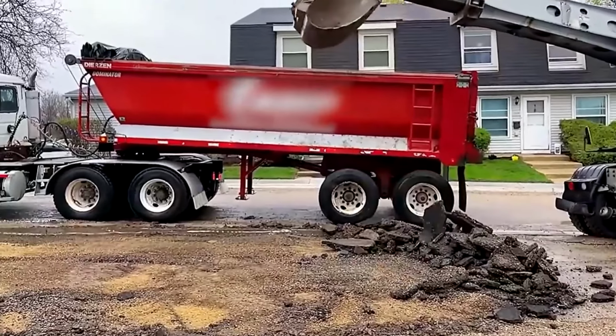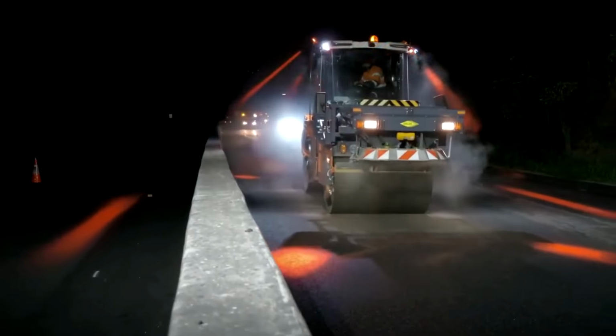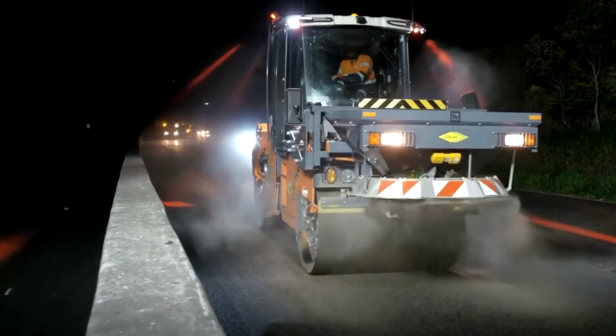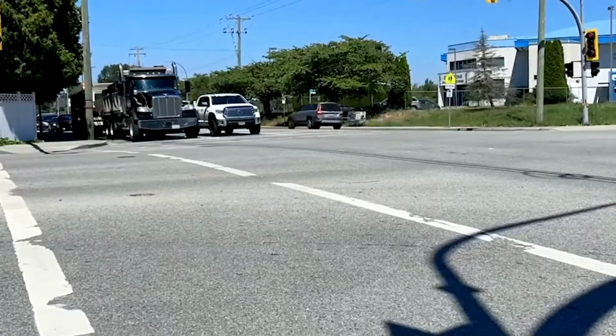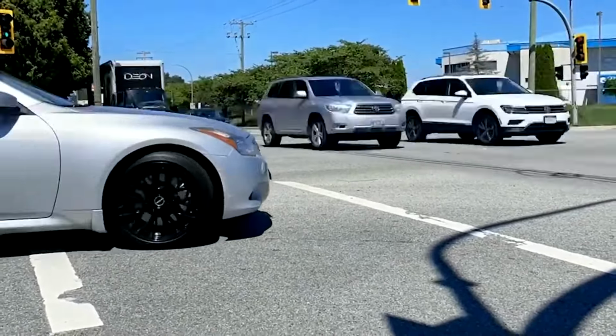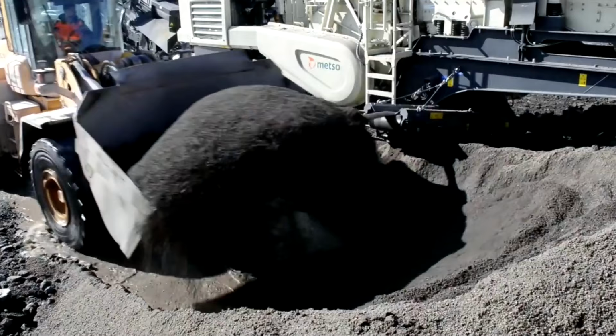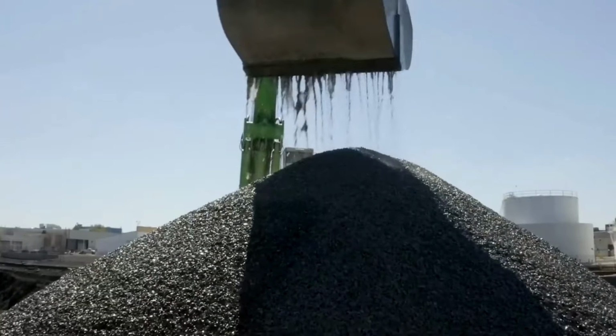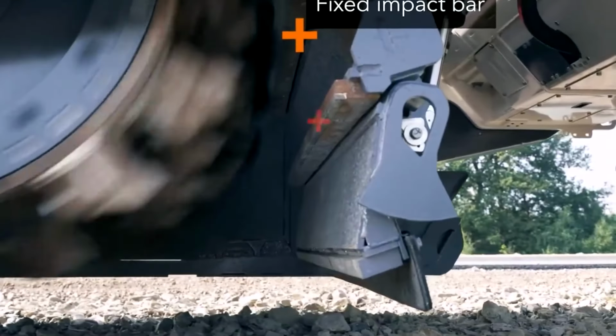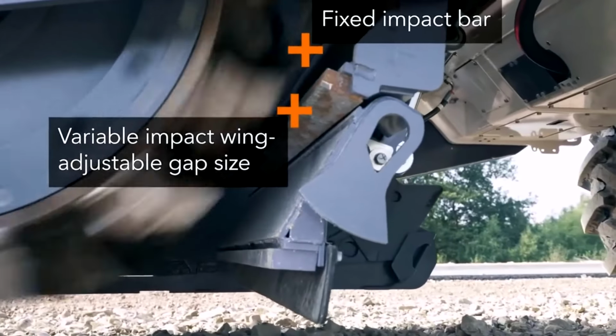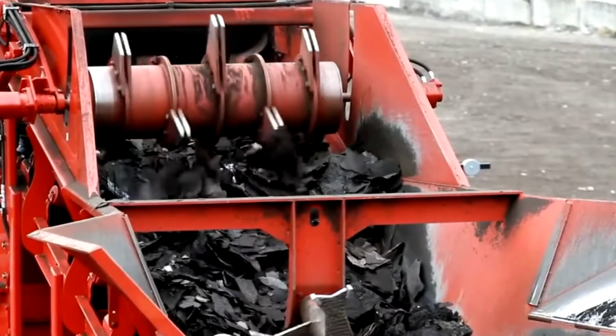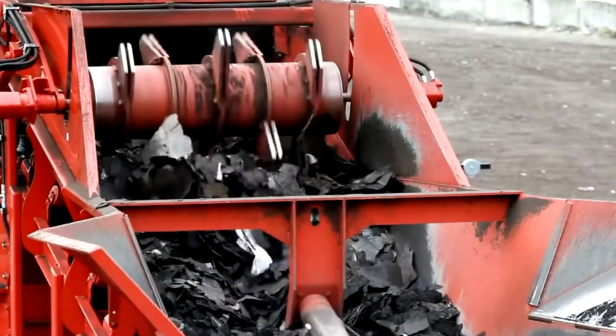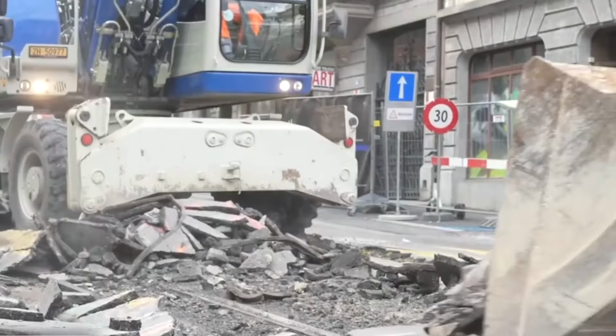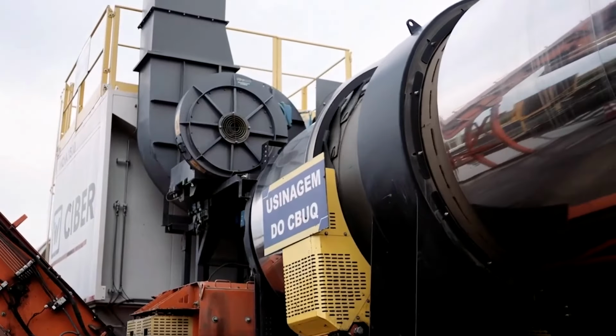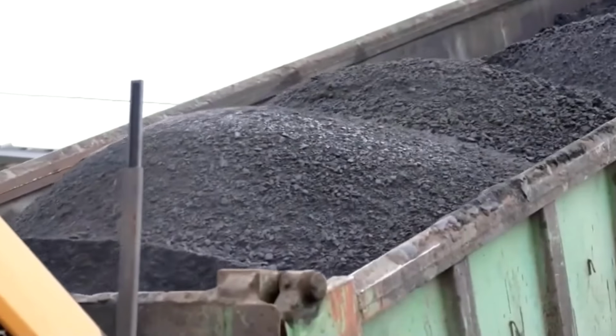On average, a single plant can handle between 100 and 300 tons of RAP per hour, recovering up to 30 or 40% of material ready for direct reuse in new asphalt mixes. This is one of the most critical stages in asphalt recycling, where old pavement is reborn into a clean, uniform resource ready to enter the drying and heating phase of the loop. Zero remains. This is the defining characteristic of the closed-loop process.